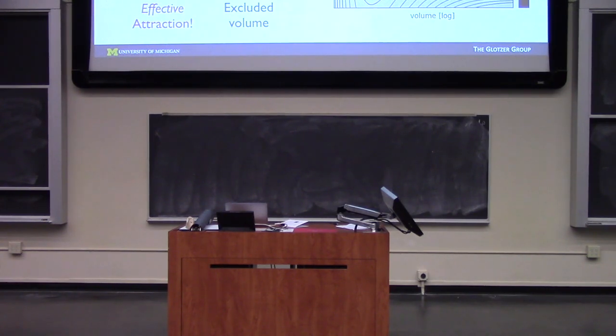I wrote effective attraction. If you don't have an attraction term, then you don't have the 1 over v squared. And without the 1 over v squared, you can't get the inflection, right? But we don't have attraction in this system. We just have entropy. So I would argue that entropy is giving rise to this effective attraction. And that's why we're able, in a one-component system, to get a fluid-fluid phase transition, which is unusual.